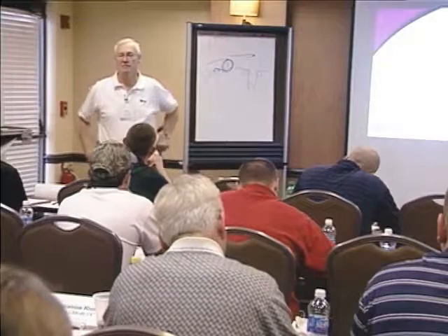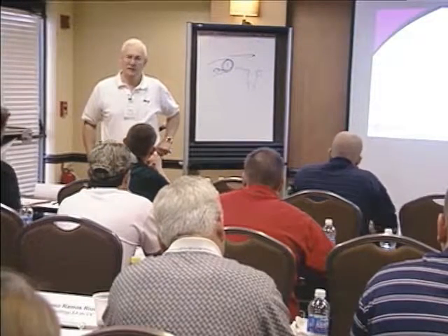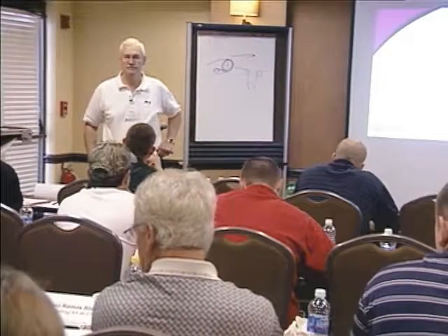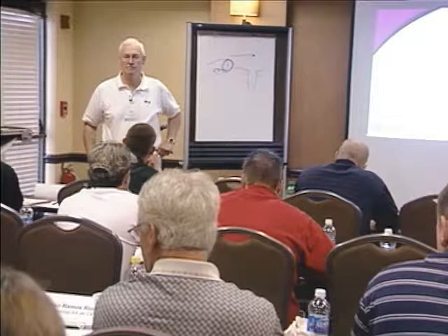We probably didn't say it much, but most manufacturers heat set their fabrics. A couple of reasons for heat setting the fabric are to get them to adhere better to the coatings and all that. But also, it's like the flannel shirt you throw in the dryer and heat set, and the sleeves come up to your elbows instead of your wrists. When they heat set these fabrics, they pre-shrink them, so that they're more able to carry a load and don't stretch as much. So they heat set the fabrics to keep that to a minimum when they manufacture a belt.